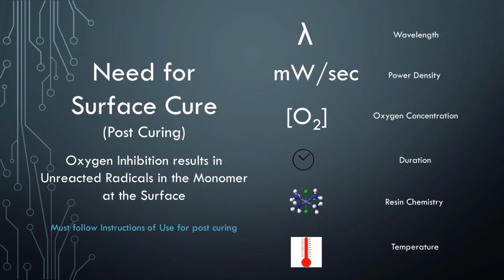But beyond curing your object, you also need to have a surface cure protocol for your resins, especially if it's going to be a biocompatible resin. So, the need for surface cure post-curing. This is after you clean your object that was 3D printed in an alcohol bath. You need to do a post-cure process, especially if it's biocompatible. What happens is that oxygen inhibition on the exterior surface results in unreacted radicals in the monomers at the surface. So technically the object is still toxic at this point until you put it through some sort of post-curing process.